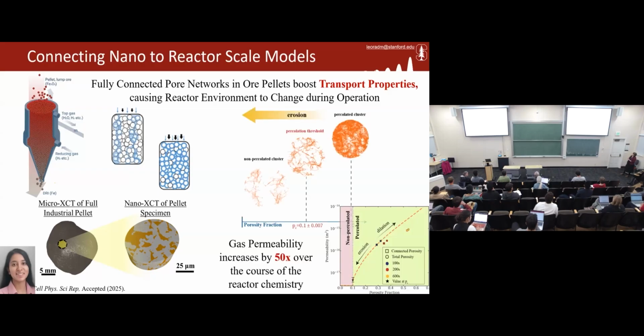And with that, she was able to use a mathematical model called percolation theory, which describes the connectivity of connected networks, to effectively describe how the flow of gas through your system will evolve based on the connectivity of the pores in your network. I.e., if you have a non-percolated cluster, you have random porosity throughout, the gas isn't going to get very far into your pellet. Whereas if you have a fully percolated cluster, so that you can blow gas from one end to the other with nothing in the way, that actually causes several orders of magnitude increase in the permeability. And she was able to build a reduced order model that turns this really complicated system into just a one-dimensional problem, which she demonstrated allows you to understand how the reactor variables change during this reactor chemistry.